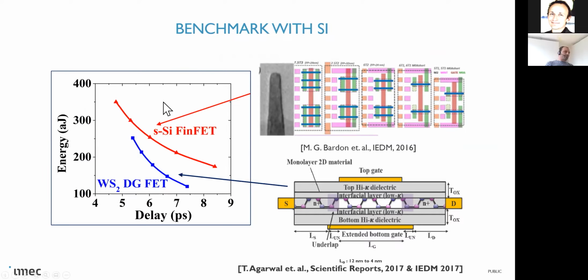So this is a prediction for N5 silicon FinFETs. And what we are looking at is energy delay. It means how efficient your transistor is and how fast you can switch your design. And there we see that for a low power application, a tungsten disulfide dual gate FET could become competitive with a silicon FinFET of the 5 nanometer technology, which is not the competition, but at least it showed that there is some promise in there.